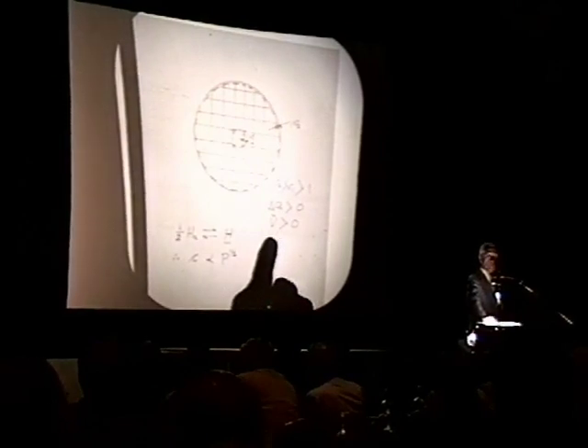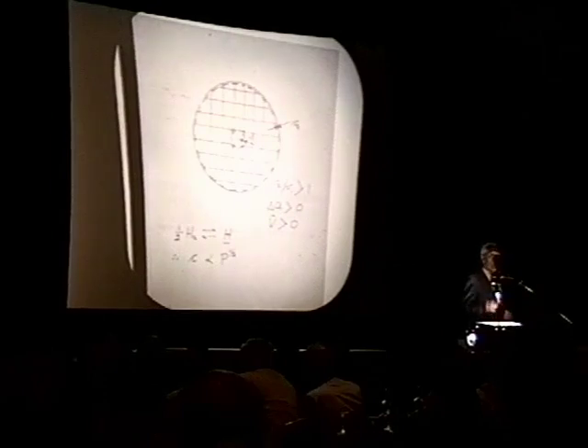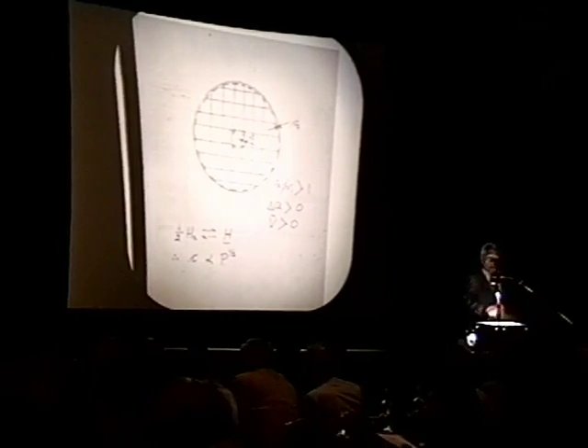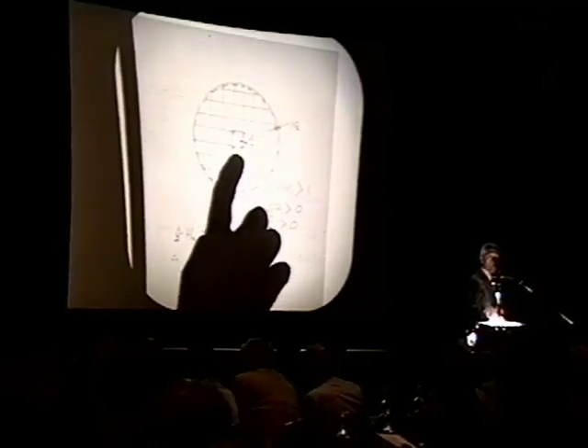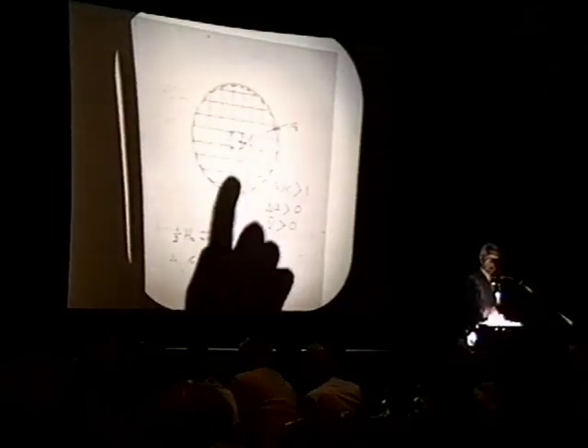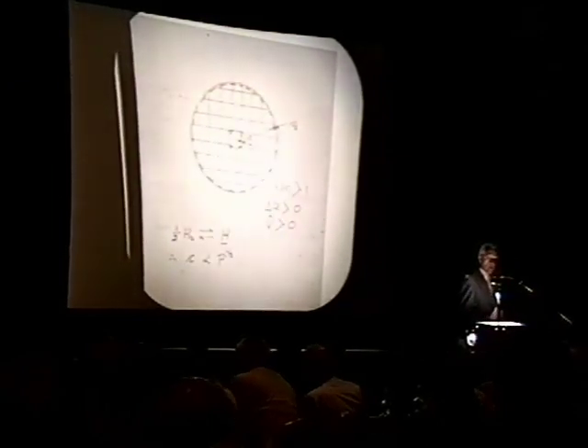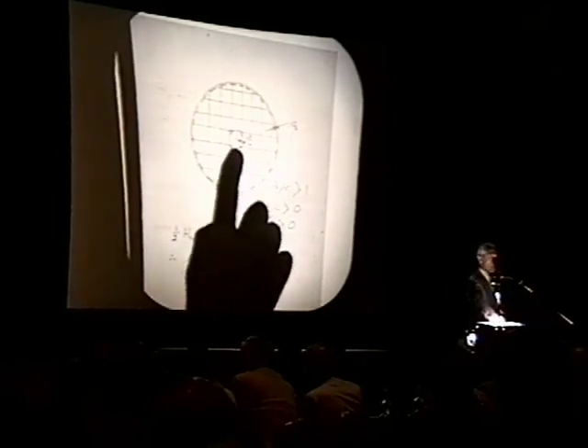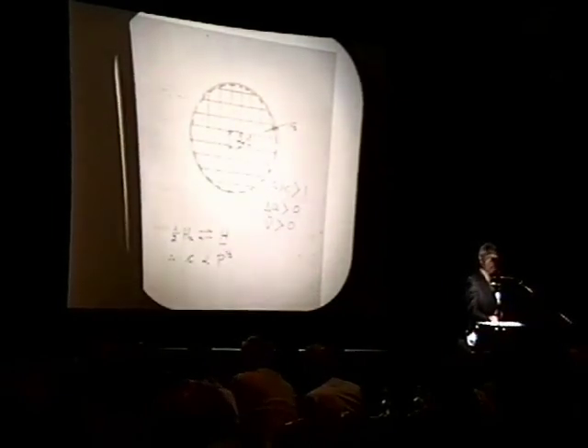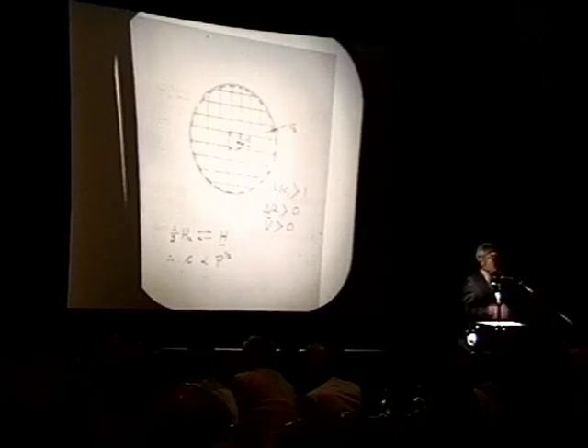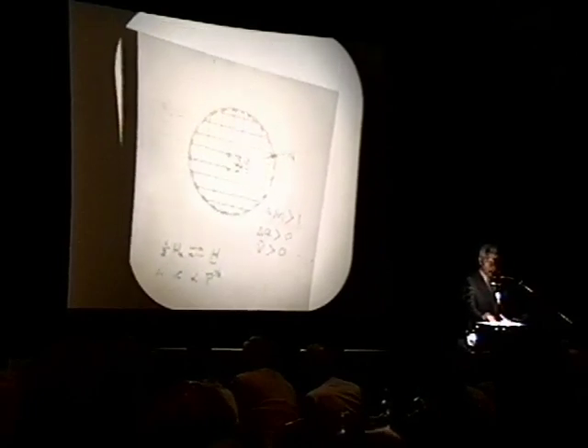This is the origin of the fact that the partial molar volume is a positive quantity, and that the lattice parameter change, delta a, is positive. The external surface of the body sweeps out a larger volume because of the distortion produced in the center of dilation, which is actually produced inside. So as you increase the number of interstitial solutes in the solid, the lattice parameter increases, and more and more room is made available for the successive insertion of solutes. That will become important for a while.